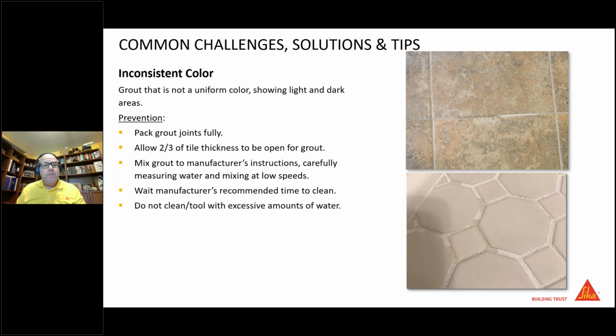But for prevention, pack grout joints fully. So we want to make sure that grout joint is as full as it can possibly be, with no hollow spots or voids underneath it. How do we know when we're grouting if we've got a full grout joint? It's not like you can see through the grout. There's a real easy indication. When you take your grout float and you're smearing it across that grout joint, pushing down into the joint, the material is actually going to speed bump on you. That's what I call it. You'll see this little hump up of the grout because it can't go any further, so it actually pushes back up when you come over with the float. That's one way to tell that you've got a full joint.